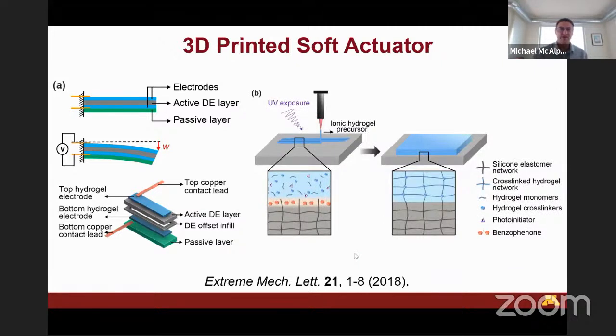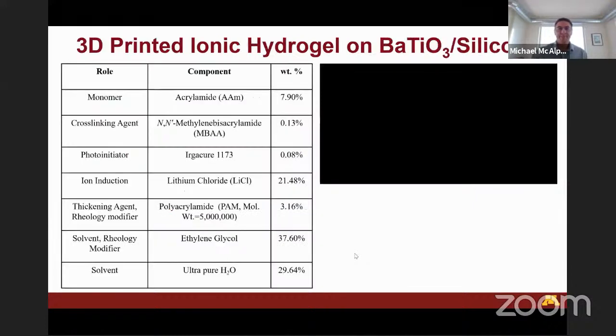We print the ionic hydrogel and then the silicone dielectric, and then we use benzophenone and activate it with UV to print the top ionic hydrogel electrode in order to bond it to the underlying silicone and create a full structure here. And as I mentioned, that silicone contains barium titanate particles. So now there are multiple materials, all built into this 3D printing process. The entire structure was 3D printed.